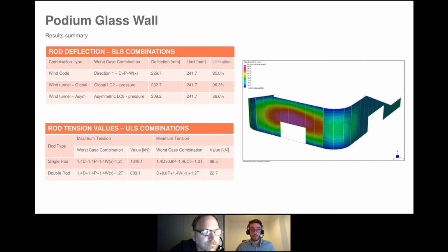For the single rod at ULS, we're seeing up to 14 tons of tension load, which, for a 52 millimeter by 45 millimeter solid bar, is quite a considerable load, while for the double rods, that are slightly smaller and also slightly less pre-stressed, we had around 8 tons of ULS tension.